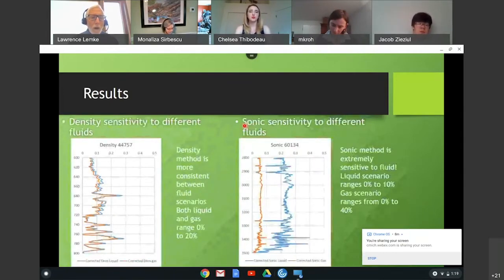How these two methods were sensitive to the different fluids. So if you look at this density curve, they're pretty similar to each other. You have the same peaks in the same spots. They pretty much match each other. But the sonic method, again, produces higher results and can have higher peaks and lower lows. So the sonic method is incredibly sensitive to the fluid that it's in or measuring.